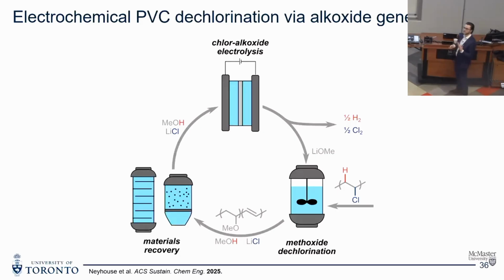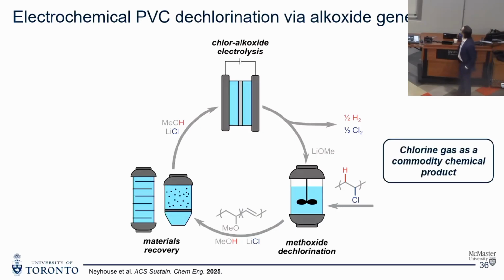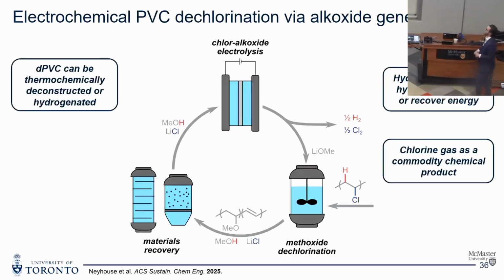And through some materials recovery and separations, definitely oversimplifying the steps in that recovery. But if we can extract out that methanol and lithium chloride, we have a circular process here where one of our only inputs is PVC, and our outputs are hydrogen and chlorine. So this is a direct conversion of PVC to chlorine and hydrogen, both commodity chemicals. So achieving this is a potentially useful pathway for enabling some chemical recycling of PVC. So we get chlorine, we get hydrogen, and then we have some dechlorinated PVC that can either be used to recover energy or can be later functionalized, deconstructed to potentially other useful chemicals.